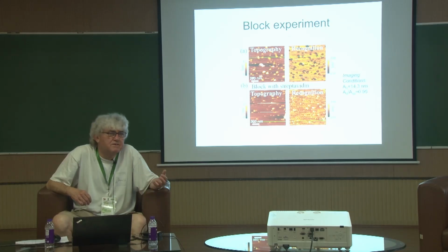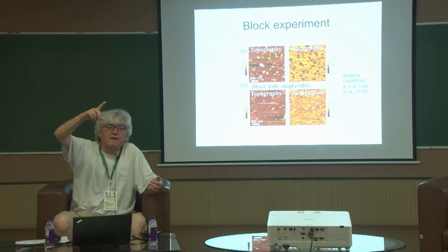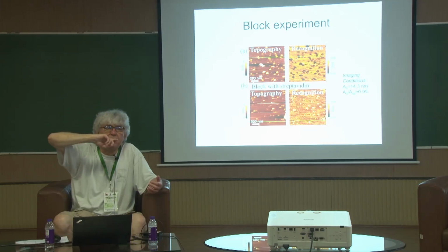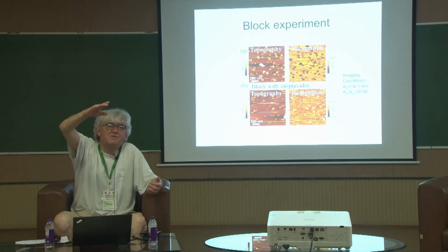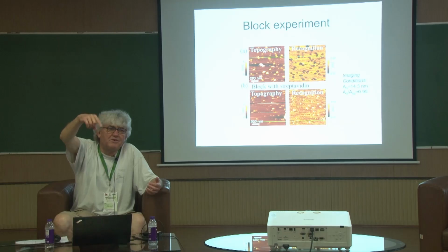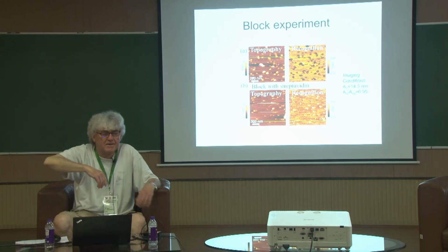You can certainly also do this material contrast type of thing. One thing could be that the oscillation amplitude is very small for the high-speed AFM. Yeah? It's just 1 nanometer, and amplitude reduction is 1 to 2 angstrom. And I could imagine that if you want to detect material properties with the phase channel, maybe the signal is a little bit lower because you just push into it very gently. This is what I could imagine.